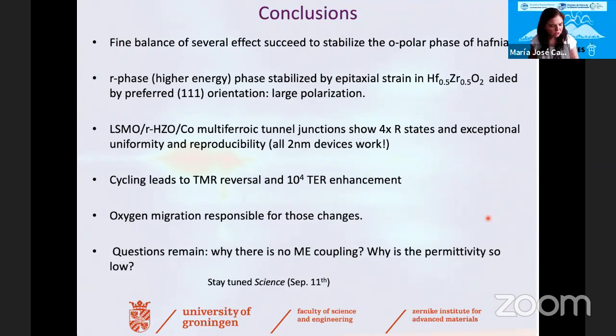So another question maybe related to the LSMO. What is the role there? Is it because it's very easy to provide oxygen vacancies, or is that the main role there? This is a very good question. We are working on this. We have a paper in preparation about that. It is a combined effect of the strain and oxygen vacancies. Again, it may be different for the orthorhombic phase and the rhombohedral phase, and it depends on the effect you want to see. If you are talking about the stabilization of the ferroelectric phase or the generation of the TER effect, for example, then the effect is different. But indeed, to have LSMO under tensile strain that is able to generate oxygen vacancies and to move the oxygen vacancies into the hafnia seems to be a very important effect.